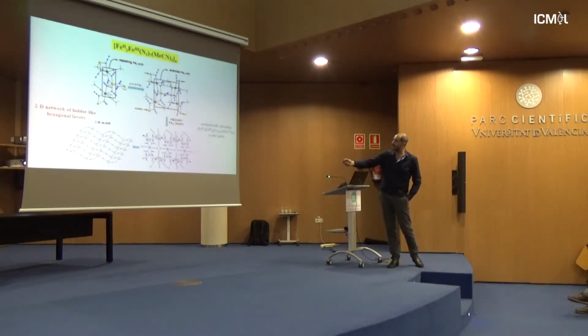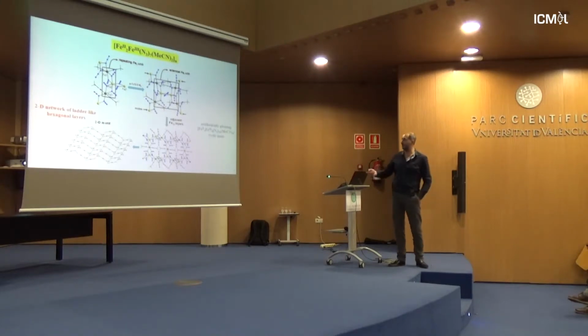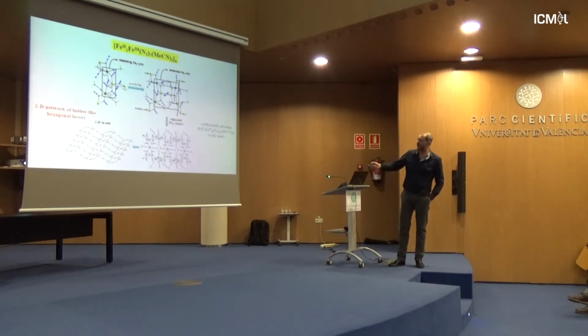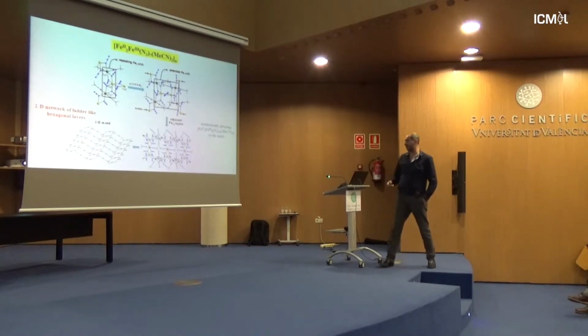This is the repeating unit of this two-dimensional coordination polymer. It has this bent-like topology. The iron 3+ is here, and these are the iron 2+. It's a mixed valence or valence-trapped compound. If you expand this structure a little bit, you see that this is extended to an iron 6. The iron 6 is then forming those aesthetically pleasing iron 10 cyclic units, and you then get that two-dimensional layer motif by using the entire network.